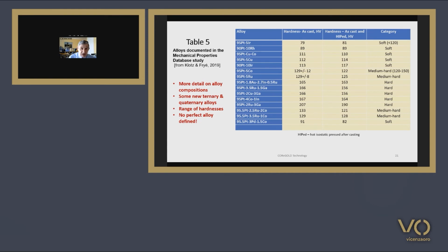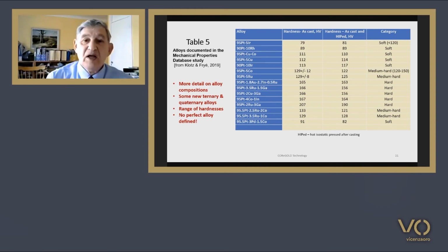This slide shows the mechanical properties that were documented in this study. And for simplicity, I only show the hardness values for as-cast and hot isostatically pressed alloys. So this gives us more detail. Ternary and quaternary alloys featured. There is a range of hardnesses, but no perfect alloy is defined.